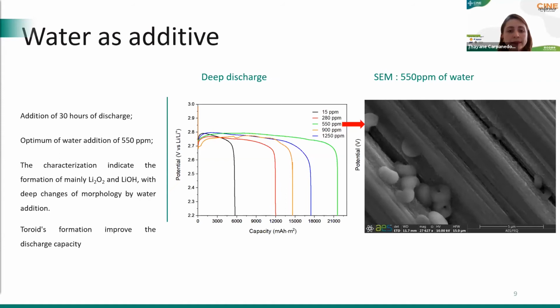And in this optimum point, adding 550 ppm of water, we verified the formation of toroids. And in the other concentrations, we have other morphologies, and with lower addition of water, we have especially films over the surface.